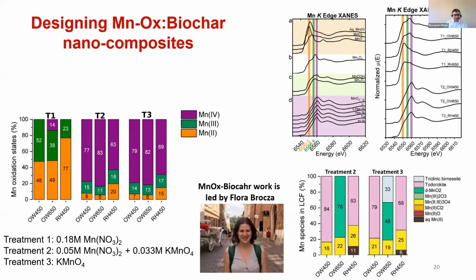So we were actually, it might have some differences, but anyway. I was saying that we tried to design manganese oxide biochar nanocomposites. We started with biochar, and then we soaked manganese nitrate into it, which is manganese 2. Then we did XANES analysis, after pyrolyzing it, to see what was happening with the manganese oxides. Is it forming manganese oxide biochar or not? It was not as straightforward as we thought it might be.